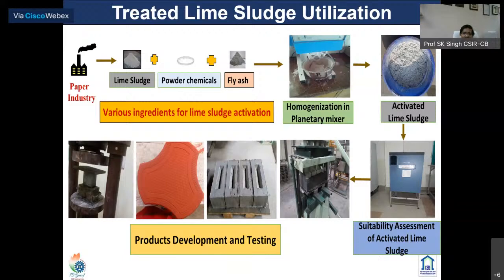What we have done is taken lime sludge. We have taken fly ash from the same industries and added it, along with some chemical for activating the lime sludge, which I'm not showing because it is our patented thing. We use a homogenization planetary mixer, and then go to our block making and other systems. For the paver blocks we have to add coarser aggregate, whereas for these we have only added fine aggregate.